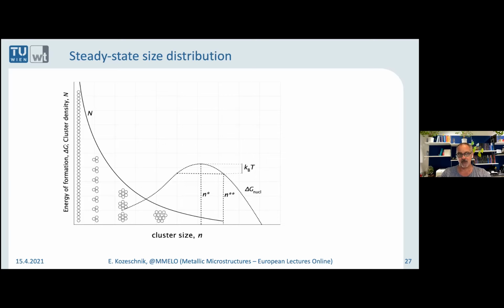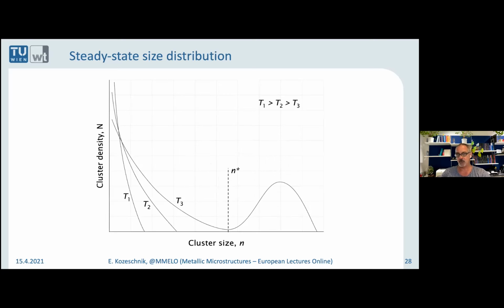Then you can think about whether this distribution, which is a function of temperature, is always existing or not. I will give you a simple example. I will consider an annealing process where we have a material and we anneal it at rather high temperature T1. The higher the temperature is, the lower is the number of large clusters, because entropy in the system will more or less destroy everything which becomes too large. So when you now quench the material into the region where nucleation occurs, then the cluster distribution must adapt to its equilibrium value, and that will take some time.